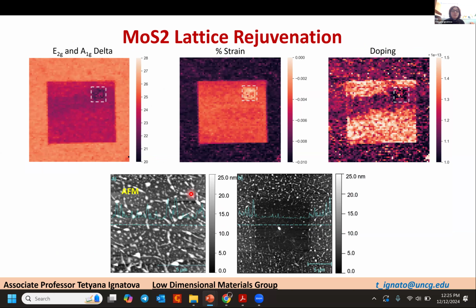Of course, we brought this sample and did Raman analysis, and we looked at how AFM profile topography will change for the sample which was irradiated with laser. This particular picture shows that definitely AFM before and after became much more smooth. We are still thinking about what is happening because we are not removing contaminants from the surface. MoS2 became absolutely flat, and we don't know why. We found that there is significant reduction of strain, but when we increased power here, you can see that the reduction of strain increased even more.